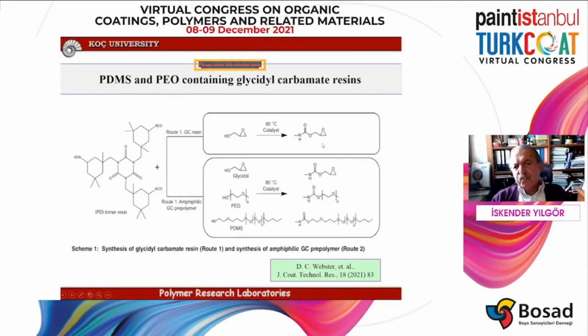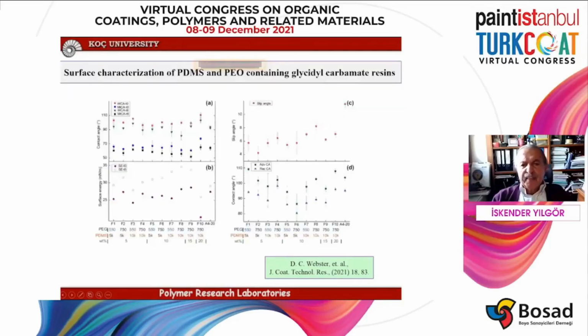This is the chemical reaction, you can look at it. This is epoxy terminated, so he cures it with amines. There are also urethanes, where he cures it with alcohols, glycols or amines. And they have done a lot of work. They prepared a series of polymers with different silicone content, silicone molecular weight, PEO content, PEO molecular weight. They looked at contact angle, slip angle, surface energy, lots of things. So they really characterized them. They also looked at AFM images to find the surface morphology and how it affects the adhesion.